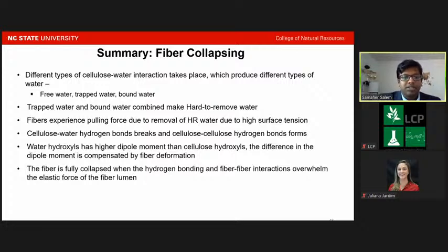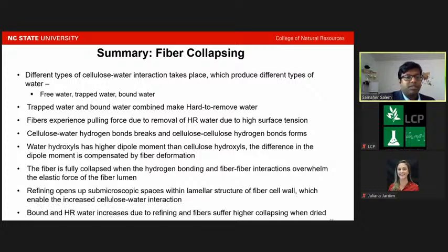So the fiber is fully collapsed when the hydrogen bond and the fiber-fiber interaction overwhelm the elastic force of the fiber lumen. Refining opens up submicroscopic space within the lamellar structure of the fiber cell wall, which enables increased cellulose-water interaction. Bound and hard to remove water increases due to refining, and fibers suffer higher collapsing when dried.